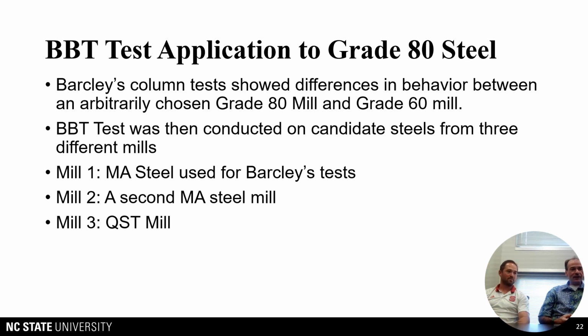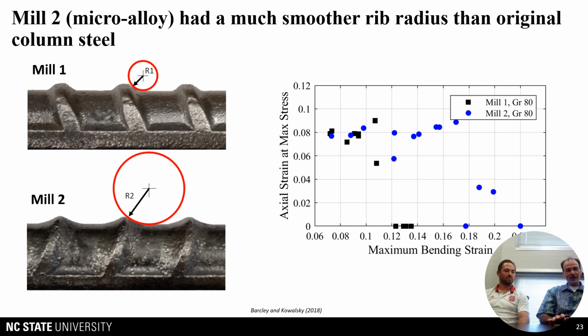Yeah, and I think once we had some confidence in it, we then applied that test to the microalloy steel that you'd used in your test, Leo, and then we'd also applied it to a second batch of microalloy steel as well as some quench and self-tempered steel. So at this point in the research, we were all interested in differences between quench and self-tempered steel and microalloyed steel, and are there differences in behavior?